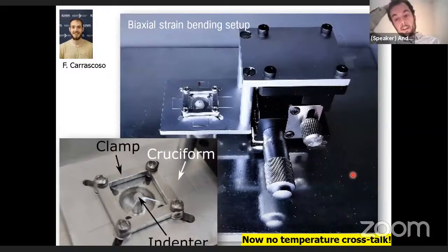Regarding the need of applying temperature to apply biaxial strain, applying biaxial strain is kind of cumbersome because you have to apply strain in exactly the same way in all directions, so it's difficult. Doing it with thermal expansion is a very simple way of achieving biaxial strain, but doing it mechanically is complicated. So recently we have some unpublished results using a technique that has been developed already in mechanics quite some time ago, to apply biaxial strain to macroscopic materials, in order to apply this biaxial strain to two-dimensional materials.